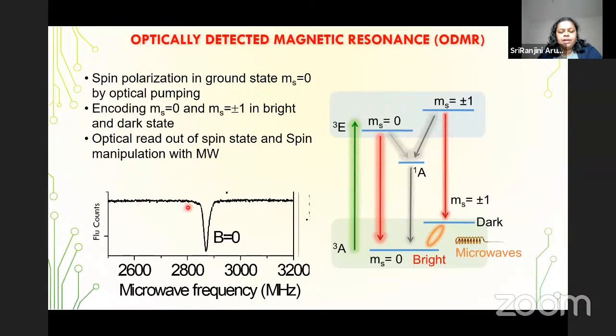So when there is a difference between the bright and the dark state, there's a dip at 2.84 gigahertz, and this is with no external applied field. And when it goes back to the resonance, goes back to the full emission, then it goes back to the baseline. So this is a very signature of the NV center diamonds.